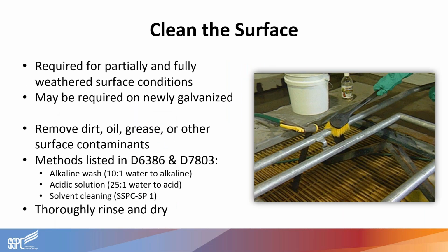So once the condition of the galvanized surface has been properly identified, or if it's been assumed as a partially weathered surface, you'll need to clean the surface of dirt, oils, grease, or other surface contaminants. ASTM D6386 and D7803 mention that organic contaminants and surface oxidations can be removed with an alkaline solution, an acidic solution, or through solvent cleaning.